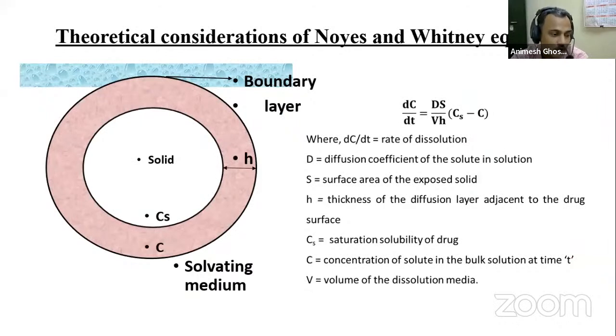So if we go to why we have taken this approach: if we can reduce the solubility of a drug molecule which is highly soluble, we can get the sustained effect. That is our hypothesis. If we go back to our theoretical consideration of the Noyes-Whitney equation, we can understand that this is the solid and this is basically the boundary layer, right? And here there is basically a two-step process in the diffusion mechanism. This is the mass transfer phenomenon, and here are two steps. One step is from the core of the tablet or core of the matrix, the drug will come to the surface, and at the surface it will form a saturated layer that is called the boundary layer, and from that layer the drug will diffuse to the bulk of the solution.